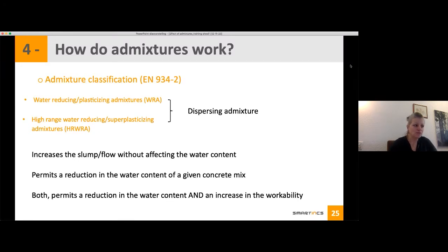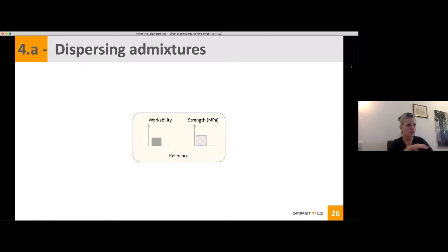What do they do? They can increase the flow of the slump, depending on what you are looking for, without affecting the water content. But they can also permit a reduction of the water for a given concrete mix. And in some cases, especially for the superplasticizers, they can do both. So you will have an increase in workability, and at the same time, a reduction of your water content.